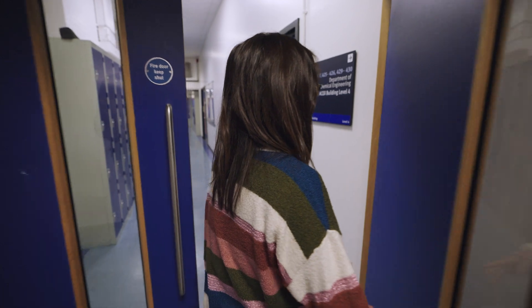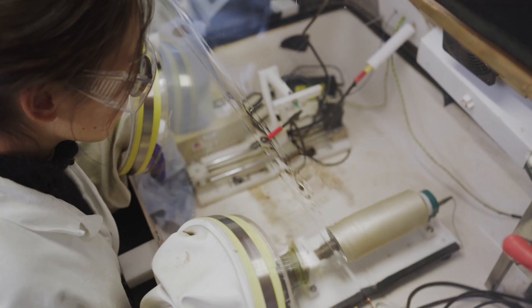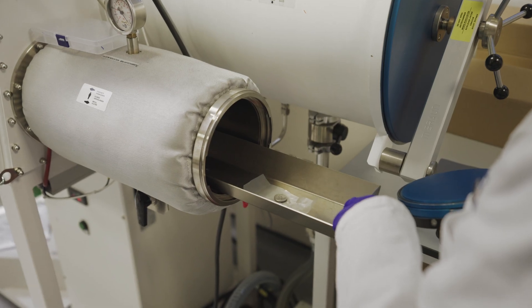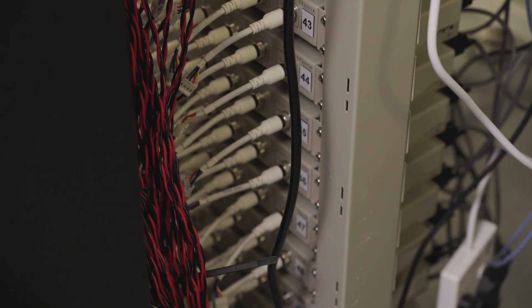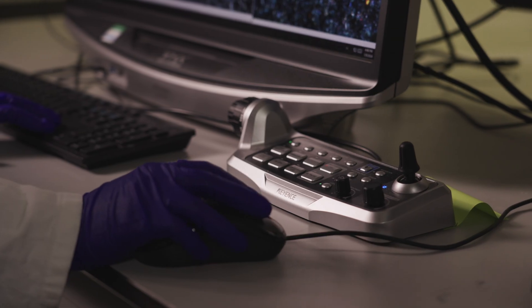My current research practice involves fabricating carbon fiber mats from lignin, a by-product of the paper-making industry. I use a process called electro-spinning to make a non-woven carbon fiber mat structure onto which I deposit lithium or sulfur to make the electrodes. These mats are then used to make and test battery designs to see how well they perform. I'm working on improving the strength and structure of these carbon fibers so that they can not only store a huge amount of energy but also provide mechanical reinforcement inside the battery.